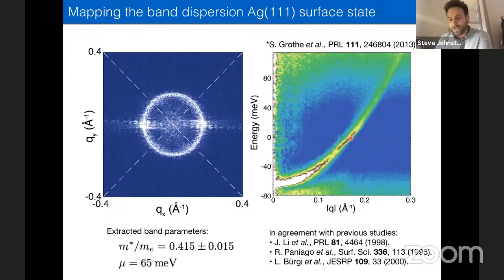What's nice about this technique is you can also go above the Fermi energy and you get access to the unoccupied states. So you see that here. And again, I really like this plot. I always remember, I showed this once to a colleague of mine in Amsterdam, and he thought this was an ARPES image the first time I showed it to him. So you do really nice band structure characterization this way.